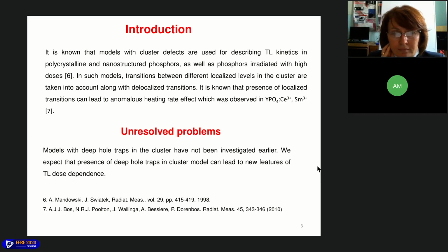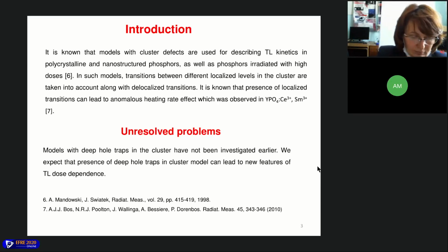It is known that presence of localized transitions can lead to anomalous heating rate effect, which was observed in several materials, for example, in yttrium phosphate doped by cerium and samarium. Models with deep hole traps in the cluster have not been investigated earlier. We expect that presence of deep hole traps in cluster model can lead to new features of dose dependence.